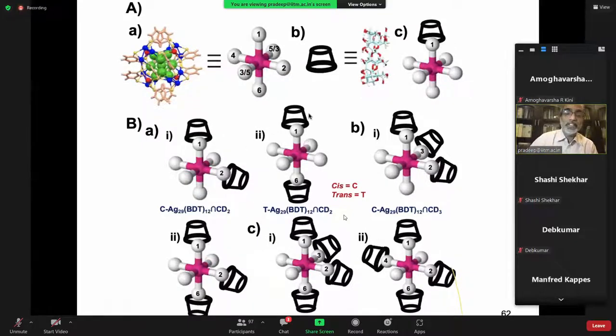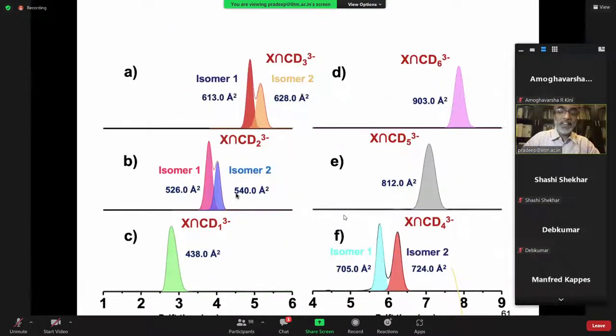For example, you take these two isomers, this is a cartoon representation. These two CDs that are present on this cluster can have this trans position or the cis position. So that gives you this possibility of creating such clusters. And this is what you see, cluster adducts.